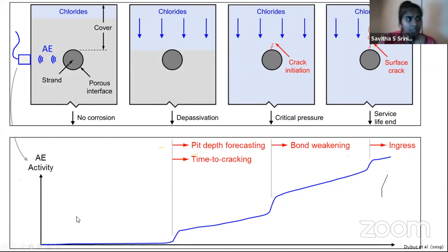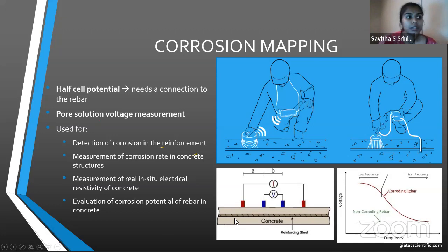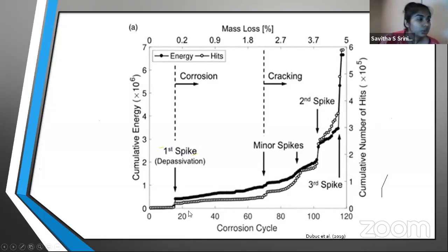So this graph shows a clearer picture of what that would look like. The black line is the cumulative energy, while the white dots are the number of hits, or the number of acoustic emission activities that happen. So when we plot this, you can easily see where corrosion starts from once the activity starts to pick up. And once the cracking propagates, you can see that it starts to hike up quite prominently. So you can kind of predict when cracking will start using this acoustic activity. It's more of a passive test because you just fit the sensor on your material and wait for it to crack.